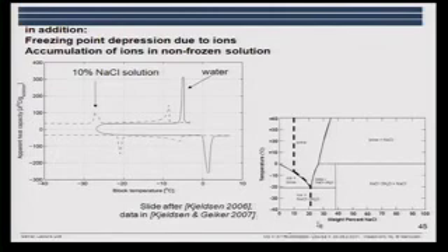So we have the phase diagram for sodium chloride, and we have a 10% solution. So we cool it, and get to this value where some of the water will freeze, and we have an increasing concentration in the solution. And we can see that we have this first freezing of the water here, and then we have the phase transformation around, well, it should be around minus 21, it's a little lower.